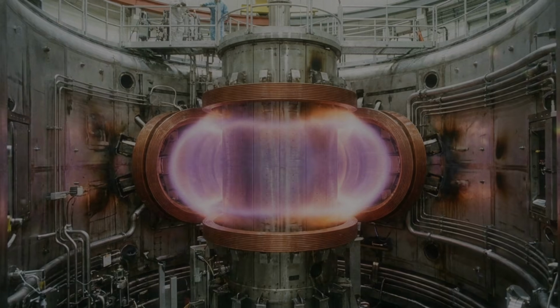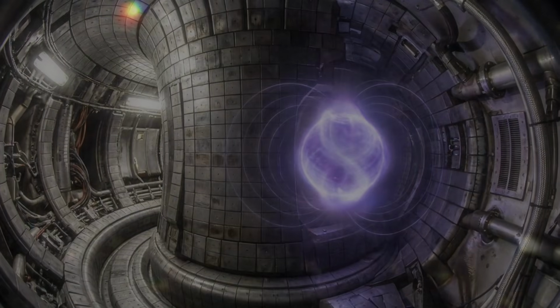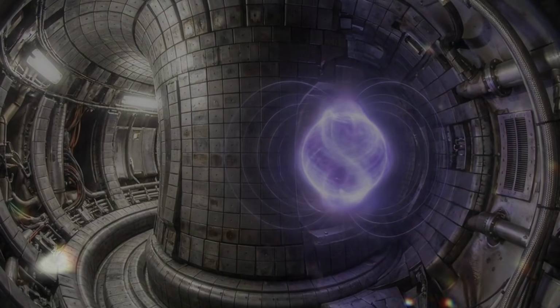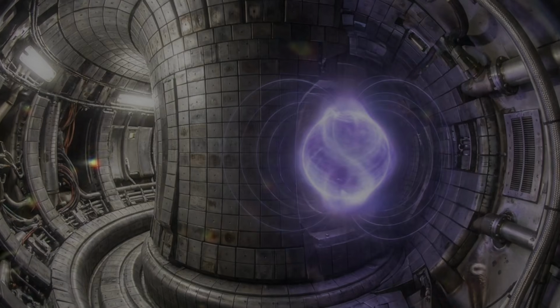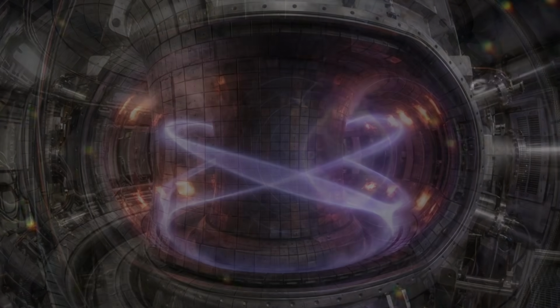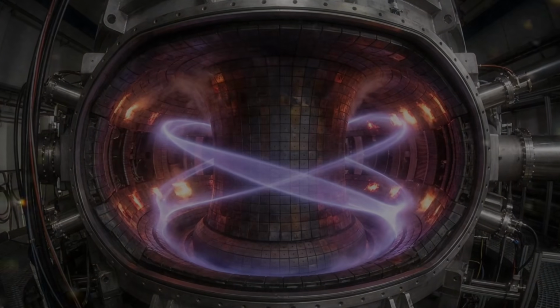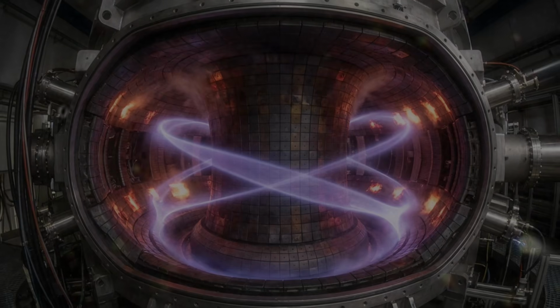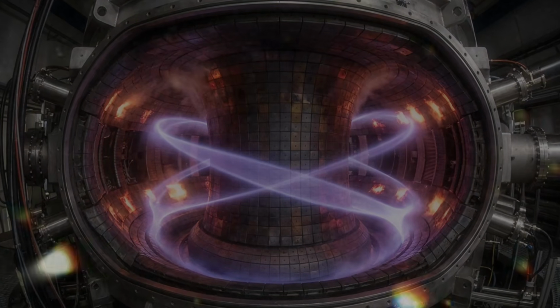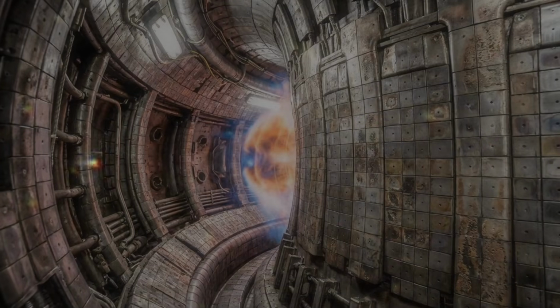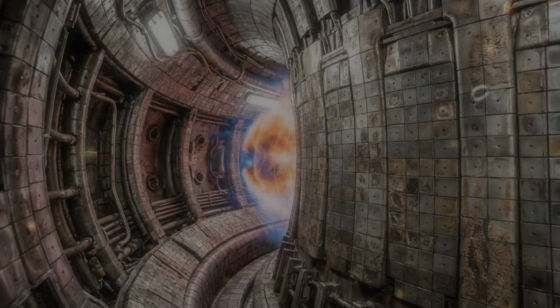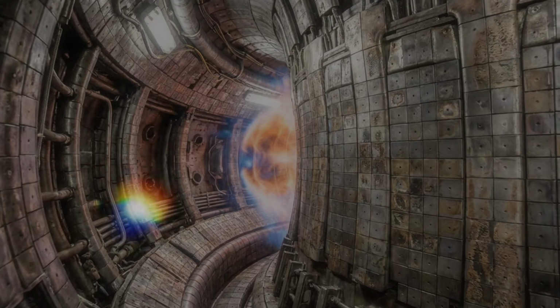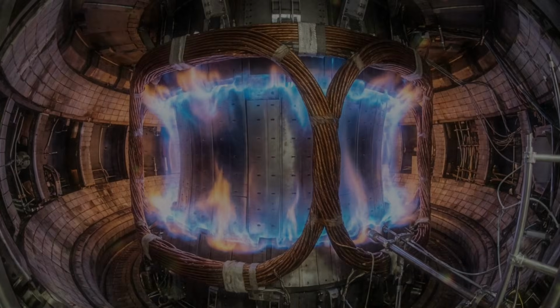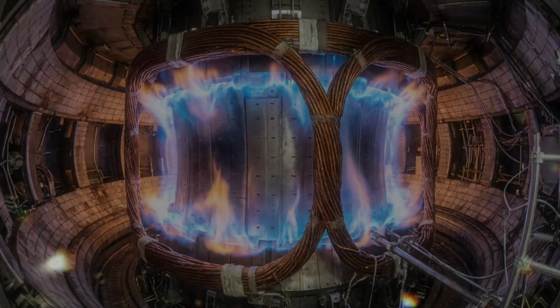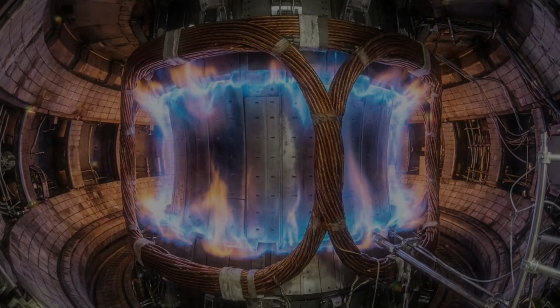This sounds simple and almost too neat. Coat the wall, clean the plasma, continue toward unlimited energy, perhaps with a small break for tea. But boron coatings come with their own complications. A coating is not permanent. Plasma exposure wears it away. Particles strike it. Heat changes it. Atoms are sputtered from it. Deposits form elsewhere. Over time, the boron layer becomes thinner, patchier, and less effective.